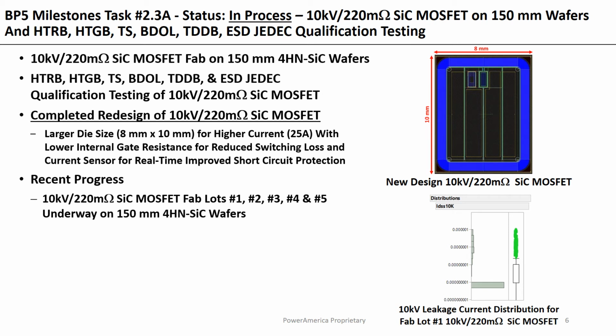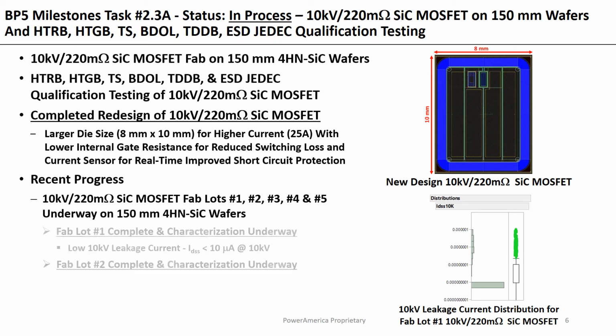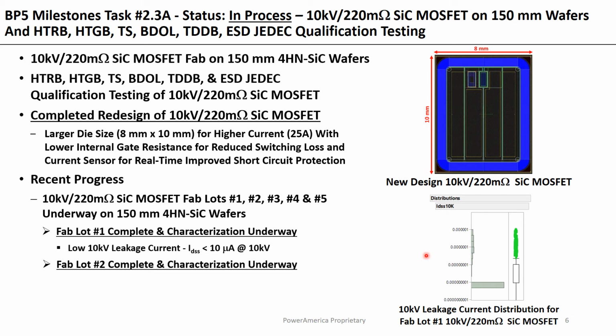Recently, we have 5 of these 10 kilovolt, 220 milliohm silicon carbide MOSFET fabrication lots underway on 150 millimeter wafers. 2 of the fabrication lots have been completed and characterization is underway, including, if you look to the right, some data showing 10 kV leakage currents, which are low, less than 10 microamps at 10 kV for these 10 kilovolt silicon carbide MOSFETs from fab lot number 1. In addition to these 2 completed fab lots which are being characterized, we have 3 more 10 kV, 220 milliohm, 150 millimeter silicon carbide fabrication lots that are currently underway.